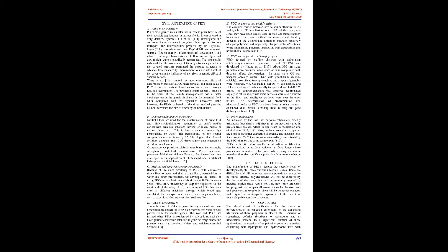Sui et al. 77 reported the effect of molecular weight on the synthesis of polyelectrolyte multilayers by combining NaPSS, poly-DADMAC, and poly-4-vinyl-pyridine, P4VP, with narrow mass distributions in the presence of added salt NaCl. They found unusual multilayering characteristics for polymers in the range of 10^4 molar mass even if the polymers are highly charged. In this range of molar mass, the surface polyelectrolyte is stripped off by its oppositely charged partner.